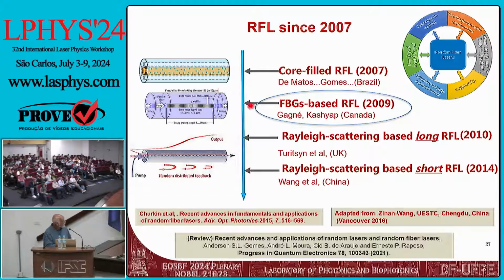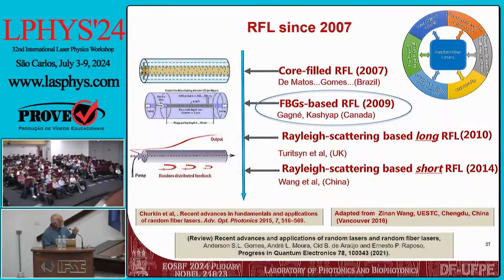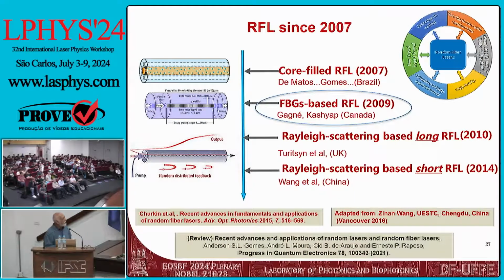And then a couple of years later, Raman Kashyap used the erbium doped fiber, and in the core of the fiber, inscribed a disordered fiber Bragg grating. So the disordered fiber Bragg grating acts as the scatterers, and that's the laser that I'm going to exploit. Then Turitsyn in the UK used the Raman scattering and the Rayleigh scattering. And at that time, they needed 80 kilometers of fiber because the Rayleigh is very weak. But I'll show at the end that you don't need that. You need only a few centimeters to have the scattering acting as the optical feedback mechanism.